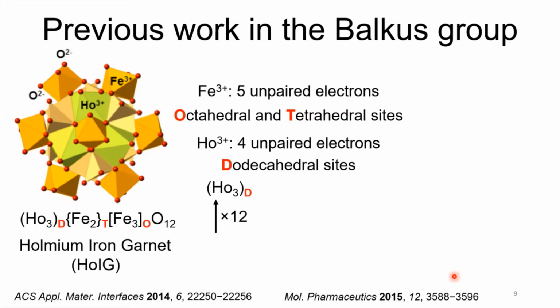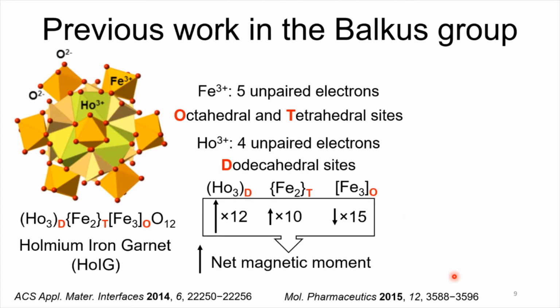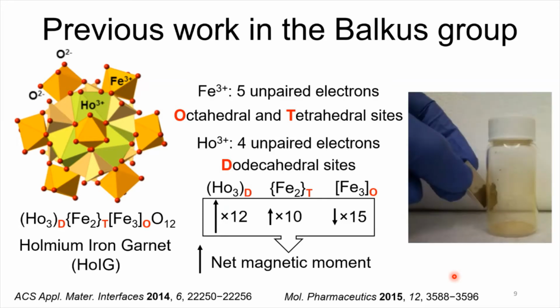This means that we'll have 12 unpaired electrons for holmium in a positive magnetic moment, 10 unpaired electrons in a positive magnetic moment for the tetrahedral sites for iron, and then 15 negative magnetic moments from the iron in the octahedral sites. But what that makes overall is a positive magnetic moment, which means our material is magnetic. This will allow us to target specific sites through magnetism.